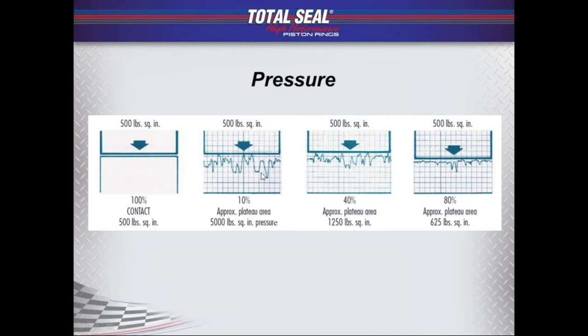As we come over to this slide, it shows almost no plateau, about 10% plateau. So now, instead of having that pressure spread out across that area, I'm sitting just on the peaks. I'm sitting on those points, on those tips. And during initial fire up, during that initial startup, with that much pressure against the ring on that cylinder wall, it's just kind of like a razor blade against it. We're going to get into a lot of scuffing. So we're not only going to wear the ring, we're going to wear the bore, and we're going to create a lot of debris that's going to get into the ring groove, into the skirt of the piston, into the oil pan. We've all had those engines we've taken apart, and you see that layer of stuff down in the bottom of the pan, and you kind of grab it up and it's a little bit sparkly. That's your cylinder wall. More than likely, you had a cylinder that was honed too rough.